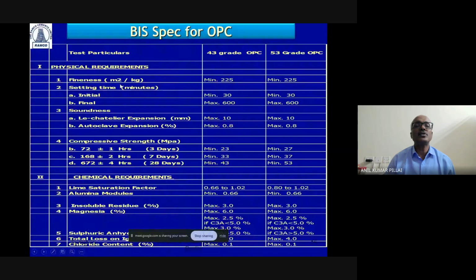But then it is also interesting to see the other parameters as far as the cement is concerned. Then you have the LSF, lime saturation factor, which is not there in blended cement. Basically, this parameter is there in ordinary Portland cement, and then you have the alumina modulus. The insoluble residue is something that you will find mentioned in the cement test report. It is very low in ordinary Portland cement, whereas in PPC you will find that the IR limit would be higher because of the addition of fly ash. And you have the magnesia percentage and sulfuric anhydride, which is coming from gypsum, total loss on ignition and chloride content.